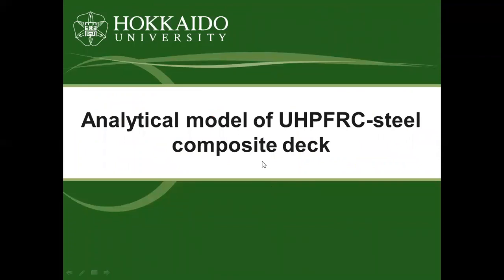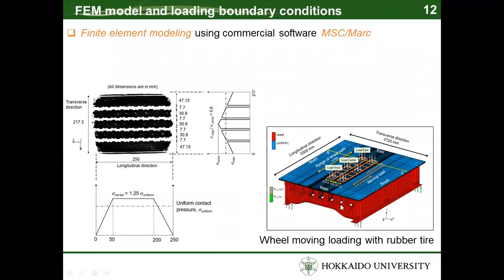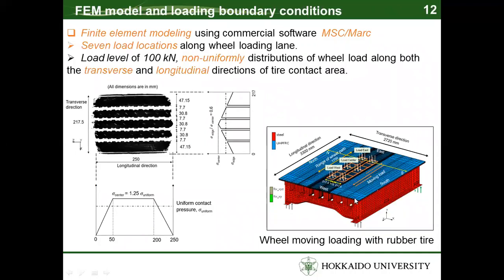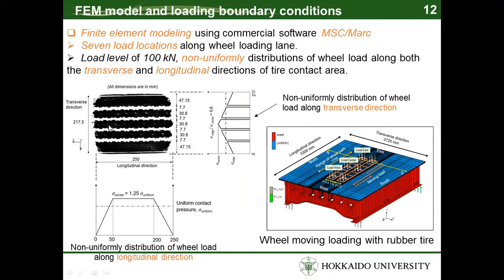Analytical model of UHPFRC-steel composite deck. This figure shows the FEM model of the composite bridge deck. Seven load locations are assigned along the wheel loading lane with a load level of 100 kN. The non-uniform distributions of the wheel loads along the transverse directions and longitudinal directions are assigned for the tire contact area.